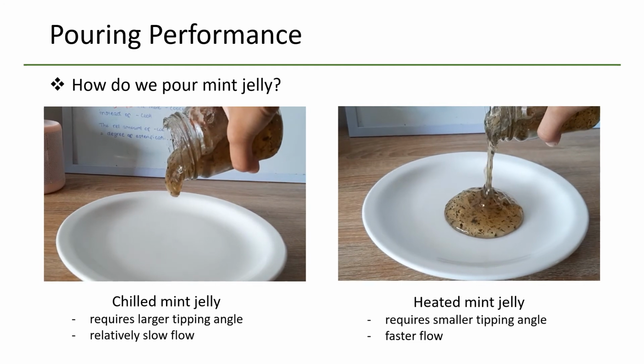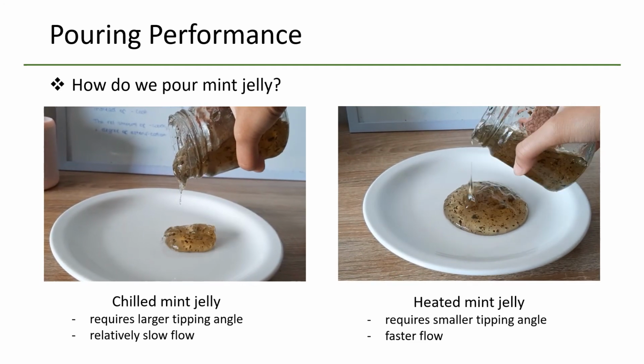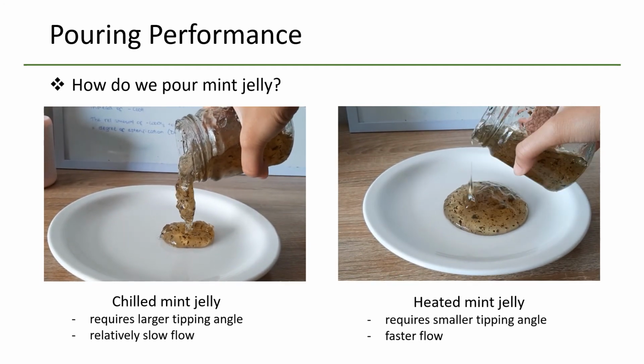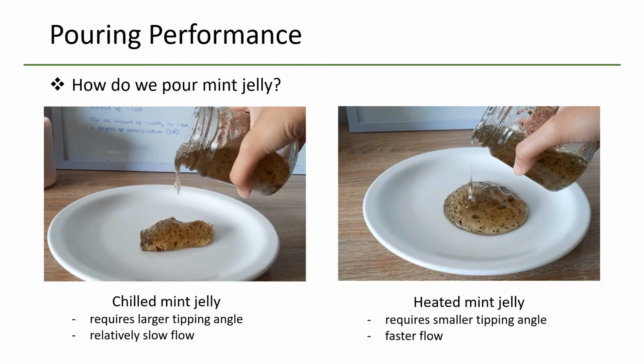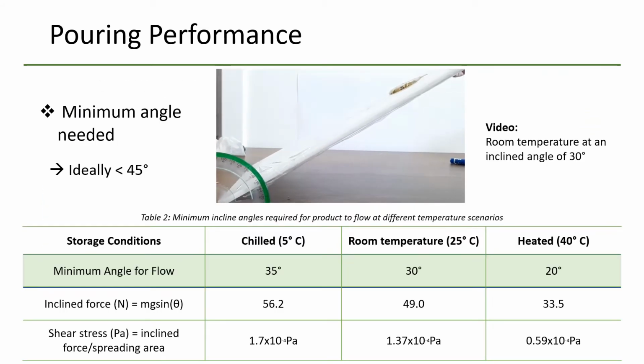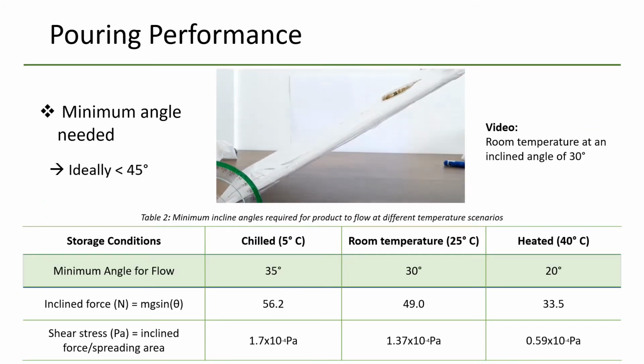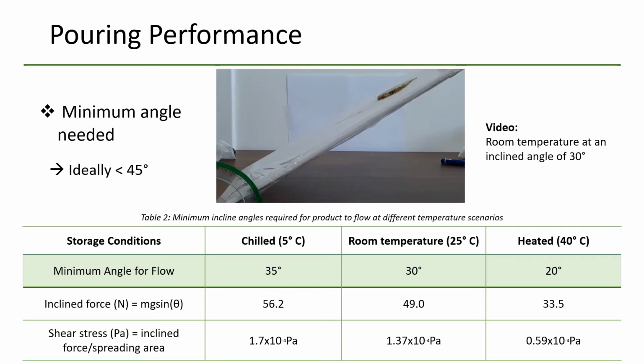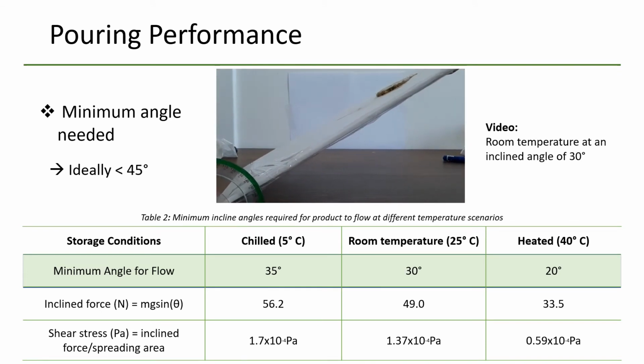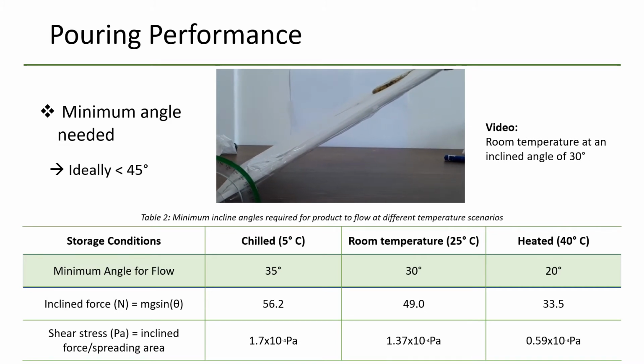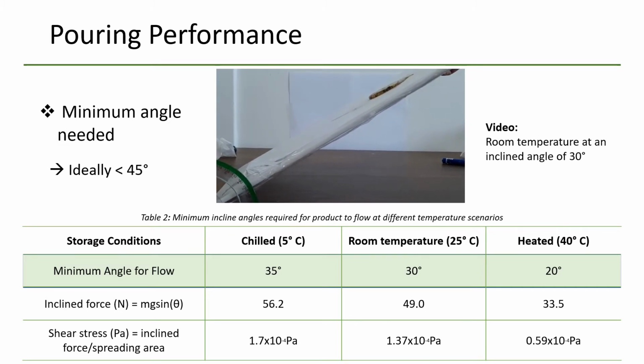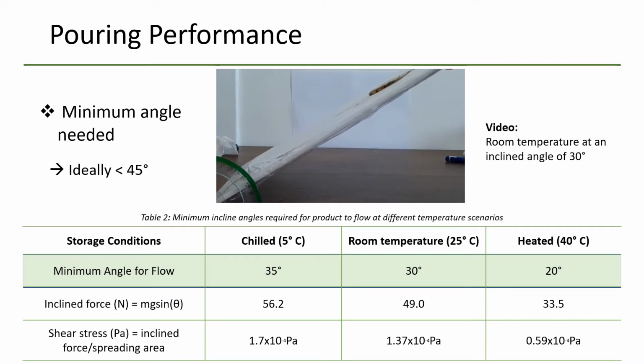As can be seen, the chilled jelly flows relatively slowly compared to the heated sample and requires a larger pouring angle. Ideally, the pouring angle should be less than 45 degrees. This scenario can be mimicked by a sliding test. The sliding test in the first presentation found that the chilled product required a minimum angle of 35 degrees for it to flow. The room temperature required an angle of 30 degrees and the heated an angle of 20 degrees. All are within the ideal range of less than 45 degrees. This trend of higher temperatures needing smaller pouring angles can be explained by lower viscosities due to changes in the microstructure.